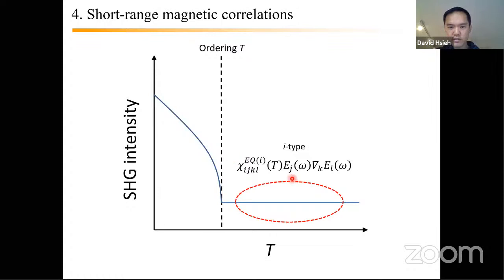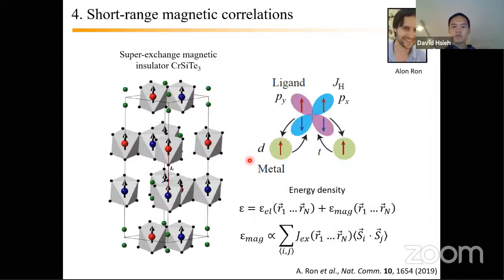So here, you could be above a magnetic ordering transition, for example, where your response is dominated by these I-type tensors. But if you have magnetic correlations turn on in this temperature window, you can have an interesting temperature dependence of your I-type tensor. That still could be somewhat dramatic. So one example, again, I'll go back to these ABX3 compounds, are ferromagnetic correlations. In this quasi 2D material, TC is something like 30 Kelvin, but it's quasi 2D. So you get these 2D in-plane correlations that build up far above the Curie temperature of the material. And basically what happens is this. The energy density of the material you can think of is split up into two parts.